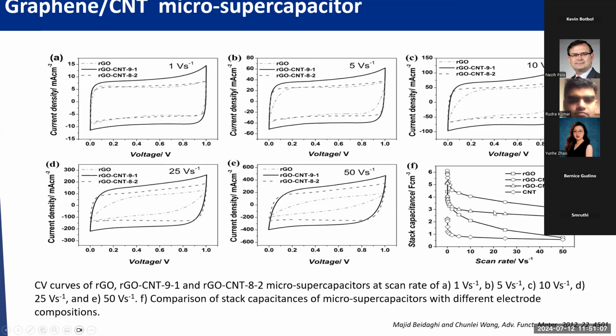So you can see the best performance for our case is 10% CNT with 90% RGO. We have the best performance, from the lower scan rate, 10 volt per second, all the way to 50 volt per second. We still have really good performance, not like pure RGO or pure CNT at high scan rate, where the capacitance is almost nothing, less than 1 Farad per cubic centimeter. But here we still maintain almost 4 Farad per cubic centimeter at 50 volt per second scan rate. So that's very good performance.